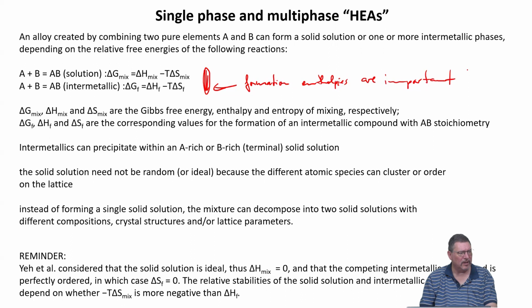And they shouldn't be too much different from the mixing enthalpies of the elements when they form a solid solution phase. Because otherwise they will dominate and only this, and then all the residual ones will form. And this is not what you're going to have.